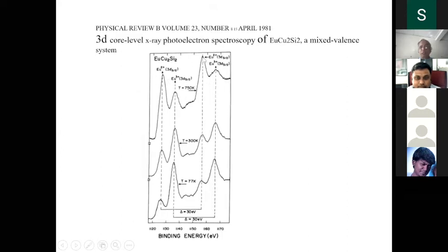There are details of spectroscopy. You can focus only on this here. You will see the europium 2 plus state peak and the 3 plus state peak. This is actually changing with temperature here, 750, 500, and 77K. A huge change with temperature. That means that even on varying temperature, the intensities of both these states can really change. These were discussed by our group here.